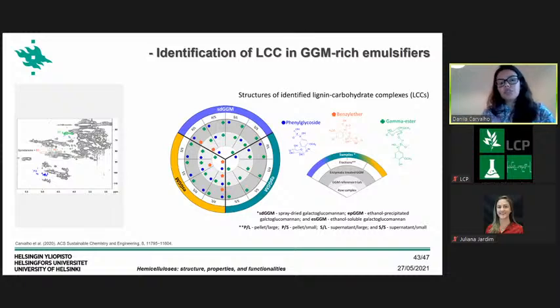And in addition to this, we also applied some enzymatic treatment in order to remove some carbohydrate fractions that were not involved in LCC bonds. And then at the end, what we could obtain as a result from this is that the presence of LCC bonds was identified. Actually, the GGM sample, the one that was obtained from the spruce, was functionalized by the presence of the LCCs. And this can also explain well why this sample acts so well as a stabilizer, because of all the explanation I gave you before, that in the same molecule we have different polarities.